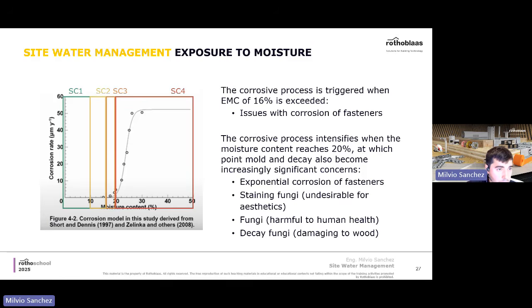And talking about moisture content itself, there is a sweet spot, which is 16%, where corrosion starts for fasteners. So anything below 16% is considered zero corrosion. Anything above 16%, corrosion starts to happen, and by 20% moisture content and above, it gets intensified, and it's going to follow not a linear curve, but more like an exponential pattern.